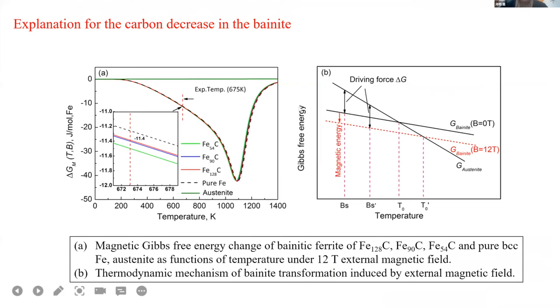So no matter how the bainite, the martensite, the pearlite, the spheroidization, the essence of the phase is regarded as a ferrite. So we calculate the different free energy versus temperature. Given the different modeling, we find that the thermodynamic driving force of ferrite by the external magnetic field is significantly decreased compared with the other phases.